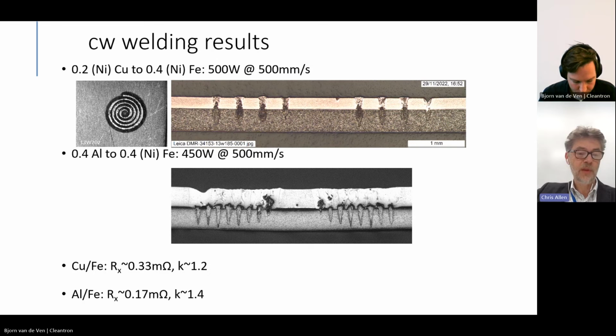And I've just included at the bottom there a small amount of information on the electrical characteristics, the electrical resistances, which is one type of critical test that we're already doing at the coupon level on these different types of materials. And you can see there is something there called K. So we have a measure of the absolute resistance in milliohms, but also the relative resistance of these welds with respect to the resistances of the two parent materials that they're joining together. So an ideal weld would have a K of 1, meaning that it is between the average resistances of the two other materials, and the higher K gets, the more resistive that particular joint is.